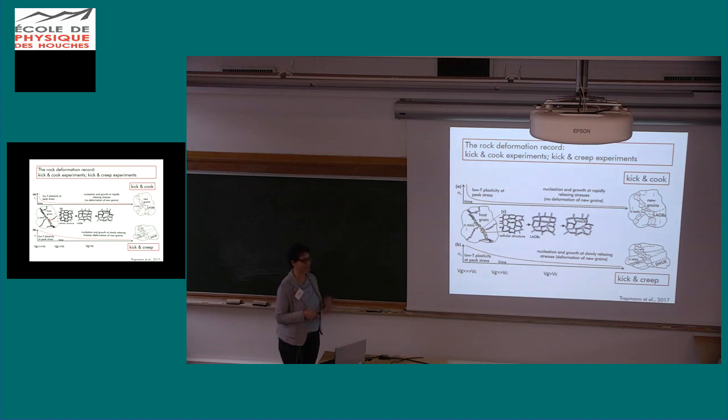And when we decrease the stresses, although the temperature and pressure conditions stay the same, we change the relative velocity between dislocation glide and climb. We are able to recover and recrystallize, which was not possible during the kick stage, whereas here is just basically dislocation glide and fracturing.